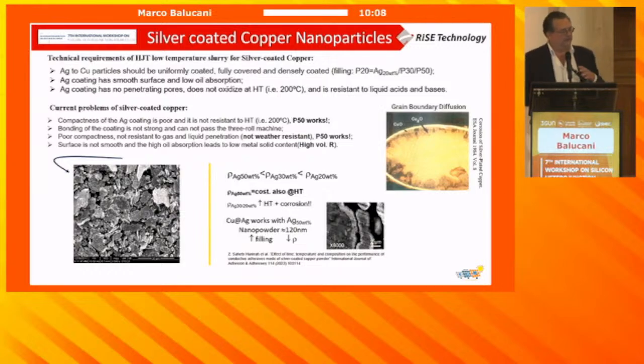If the coating, we don't want to have pores, we don't want oxidation. But in reality, and this was proved by ESA, whatever you deposit on top here, you will have oxygen passing through grain boundaries. And that's what is called the red plaque. So what you will face depends on how much time, but in any case, if you have oxygen and you follow the chemical equations, you don't need water. It's enough to have only oxygen. You don't need a wet ambient. You will have some red plaque. You will have some oxidation.